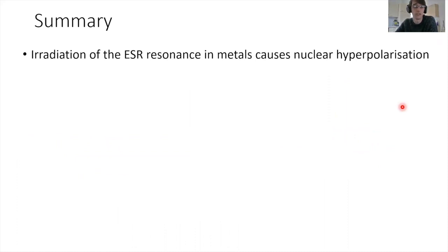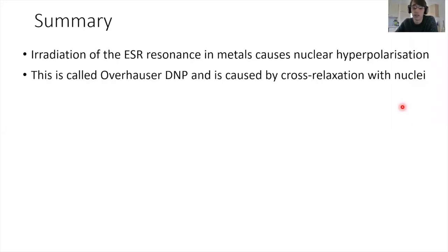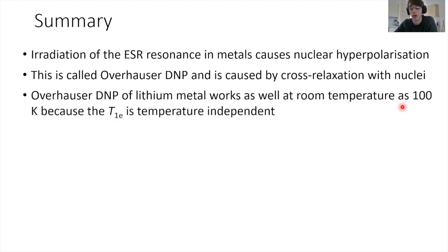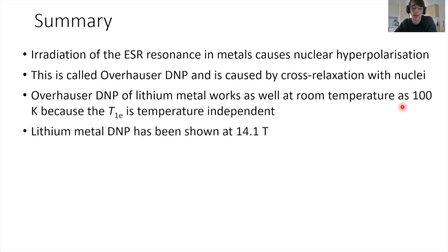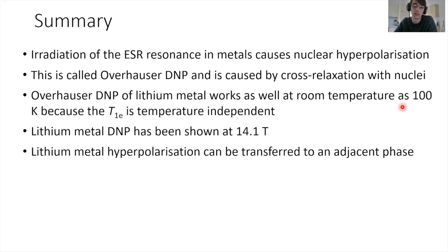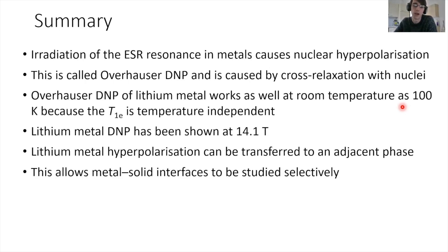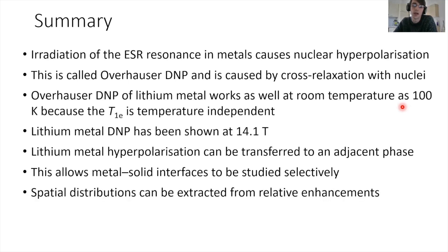Okay, with that, I'll just sum up this section. So irradiation of the electron resonance transition in metals causes nuclear hyperpolarization. This occurs by cross-relaxation of nuclei and is known as Overhauser DNP, as first demonstrated in 1953. For the case of lithium metal, you can do this at room temperature because the relaxation is temperature independent, and that works just as well as at 100 Kelvin. What we've done differently, we've demonstrated that this also works at high field, which we need for resolution. We then showed that you can harness this hyperpolarization and transfer it to an adjacent phase, and this allows you to study buried metal-solid interfaces. In particular, because we control where we introduce the polarization in the metal, we can extract spatial distributions from the relative enhancements of different species.